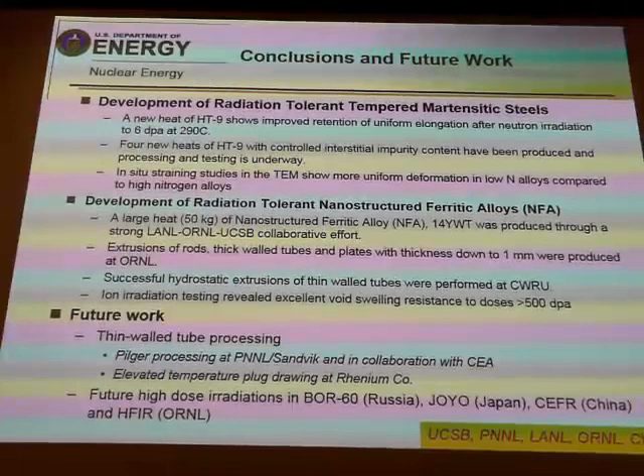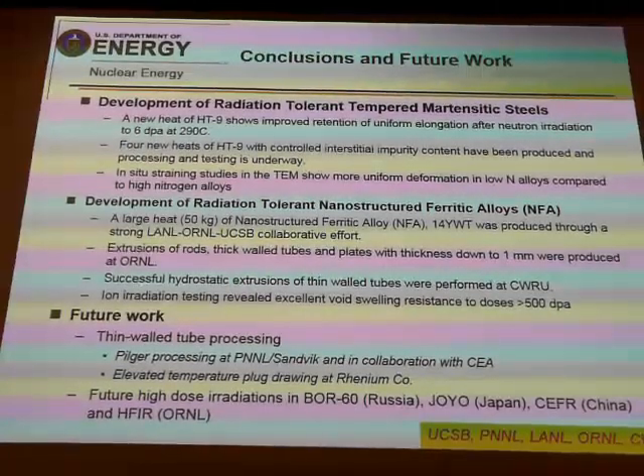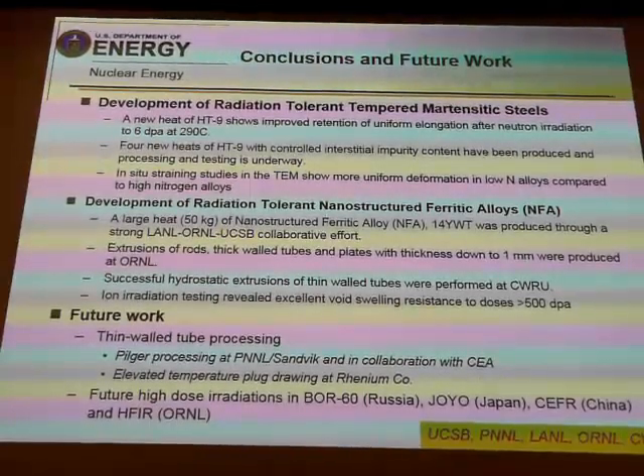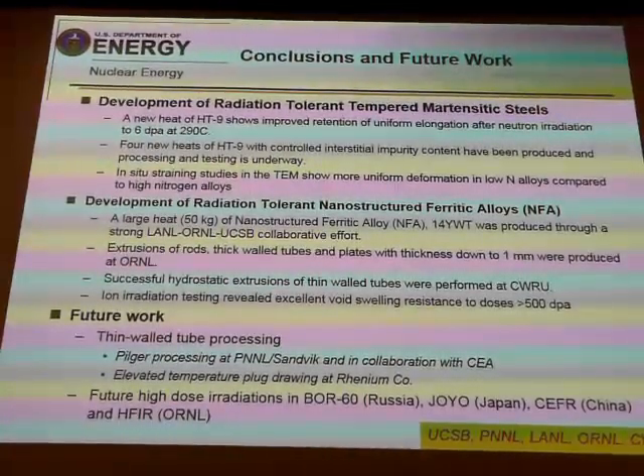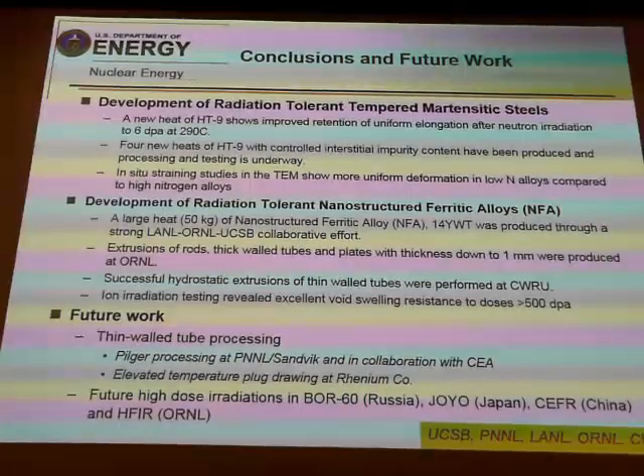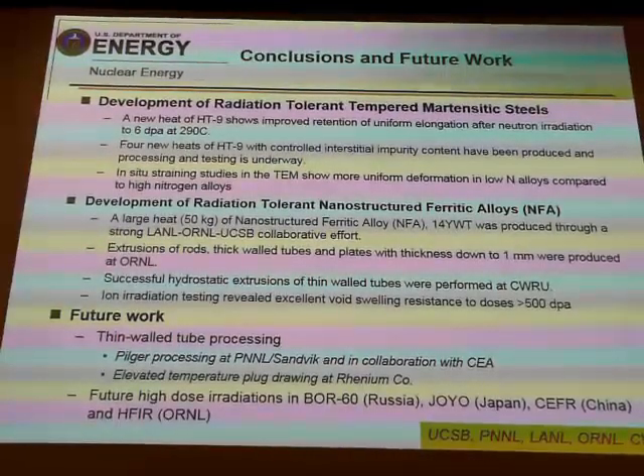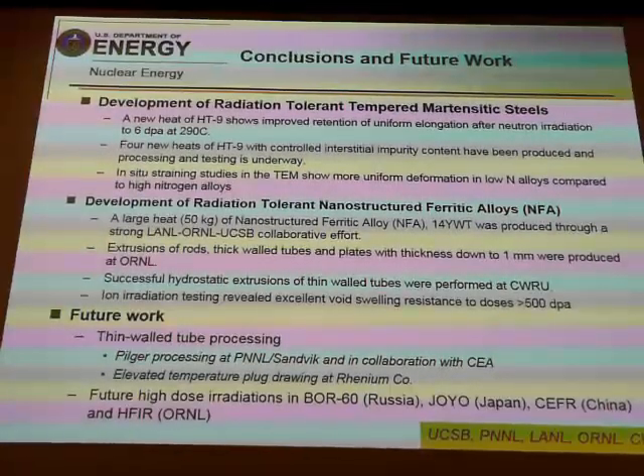Yeah, we've done some high dose ion irradiations on our ODS alloys, and it's actually similar to what other people have seen. Between 400 and up to about 600 degrees C, you still see the oxide particles uniformly dispersed within the material. We do see a slight reduction in size, but we don't see a complete loss. So, I mean, nobody knows what's happening. Maybe the oxide particles are going into solution and precipitating.